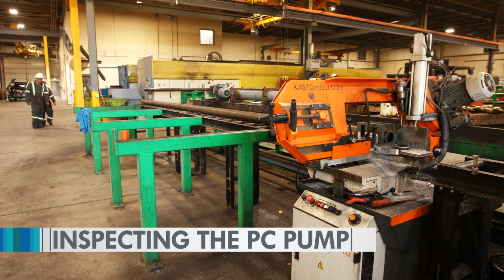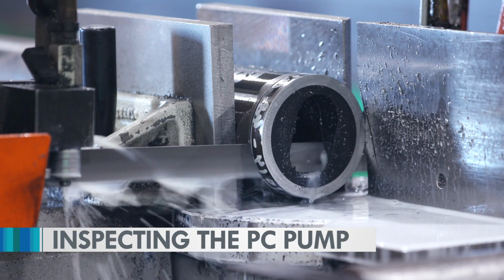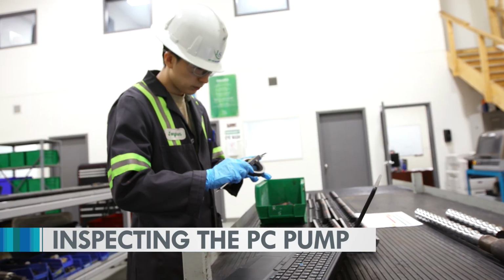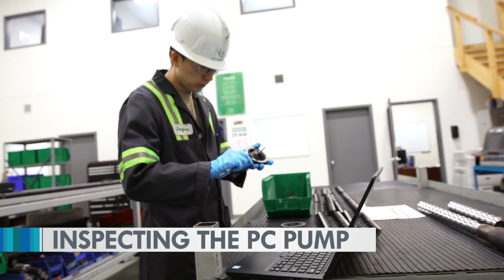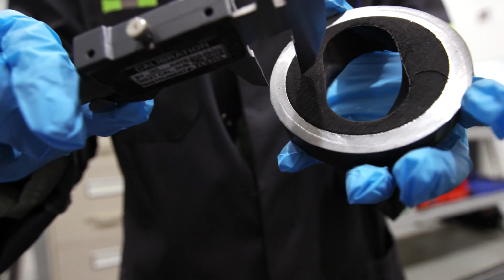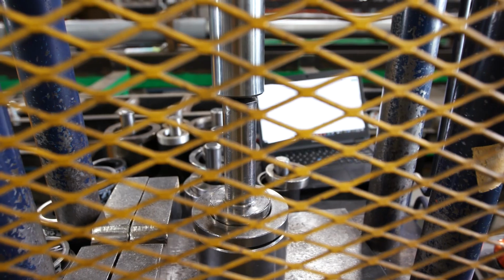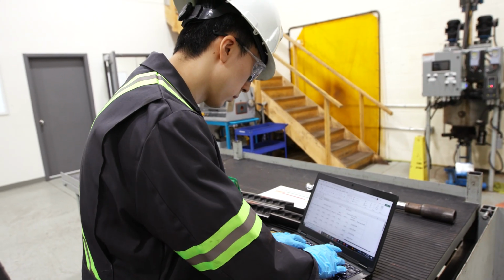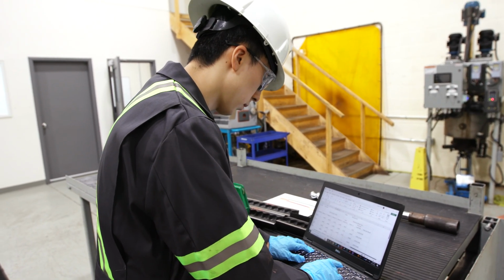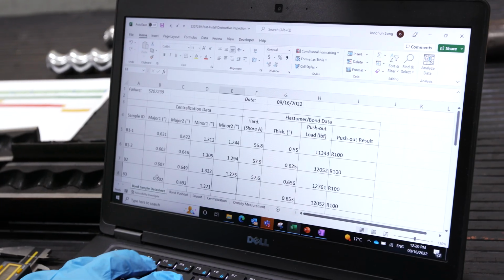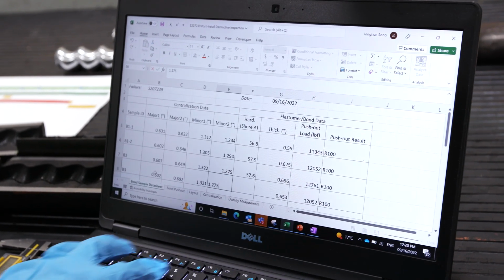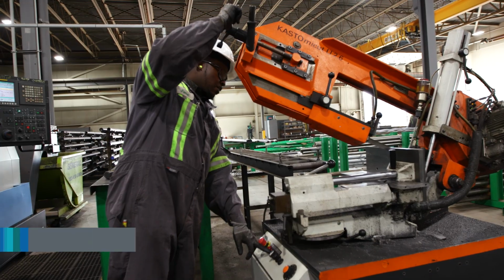Within the inspection area, stators have thin bond samples cut from both ends. These samples are first used to verify the elastomer hardness and then subjected to a push-out test to confirm the desired bonding characteristics. Additionally, every stator has its internal dimensions measured along the length to confirm it meets the engineered size to support proper pump sizing and operation.